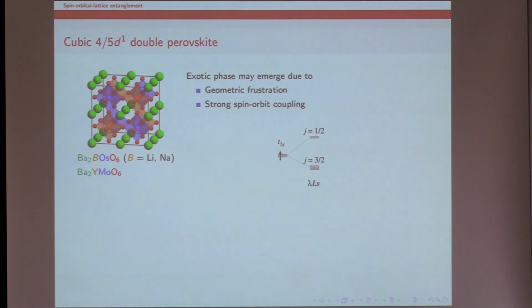First of all, the magnetic site forms an FCC structure, so this is geometrically frustrated. And moreover, there is strong spin-orbit coupling on the magnetic site. And in the case of a d1 system, local electronic spin-orbit coupling makes the ground spin-orbit coupled state a four-fold degenerate state. Because of this high degeneracy, the exchange interaction becomes of multipolar type.